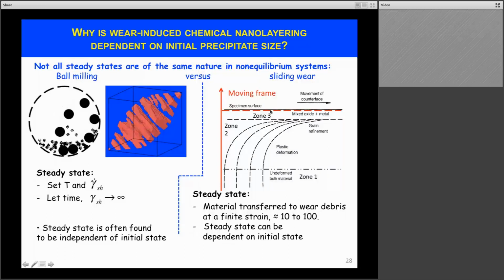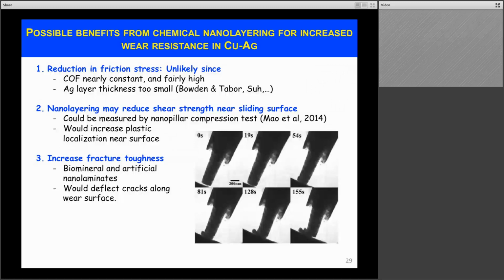And so the steady state wear response is one where these pieces or volumes have not been exposed to an infinite amount of strain, but a finite amount of strain. So, the possible benefits of this nanolayering we've considered, and in particular, we know that it's not due to reduction in friction. We showed through other tests that nanolayers can localize plastic deformation at interfaces, and this is what you see here in this nanolayer tested in situ in a transmission electron microscope.